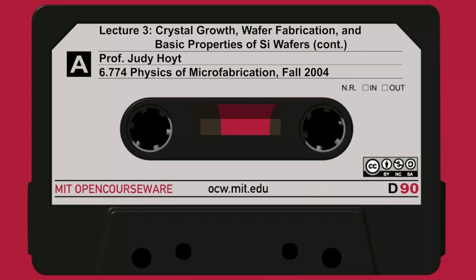So what this means is that in intrinsic material, so it's intrinsic at that temperature, the neutral vacancy, which does not depend on the Fermi level position, is going to be the dominant vacancy charge state. It's V0 that dominates when you're in intrinsic material. As I now take this Fermi level and move it up, we'll see that these guys will dominate. You get more and more of these charged vacancies, and if I move it down, we'll get more and more of these. But if we're neutral, if we're intrinsic, then it's the neutral vacancy concentration that dominates. And we'll show some equations for how to actually calculate that.